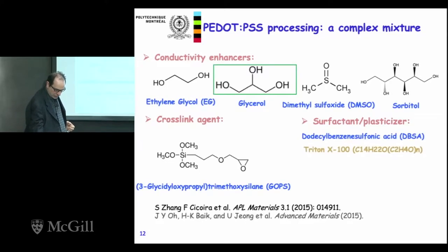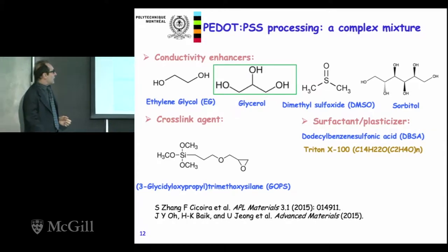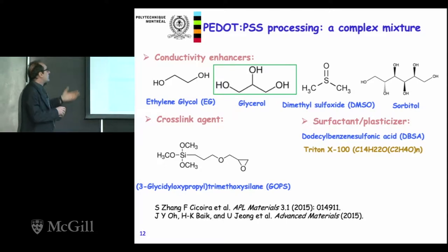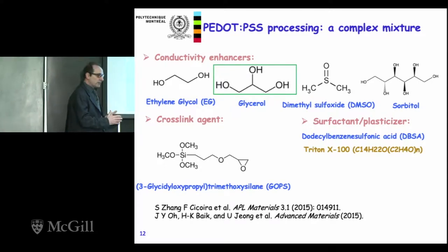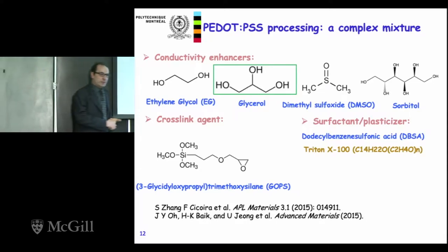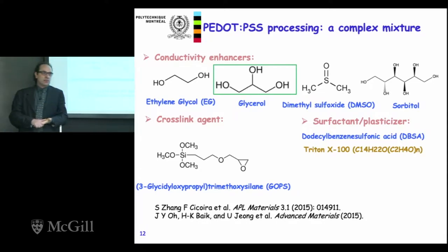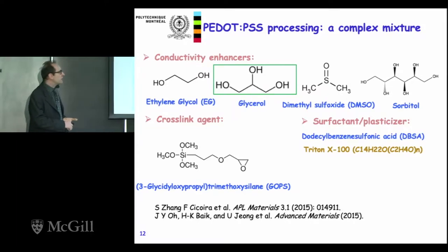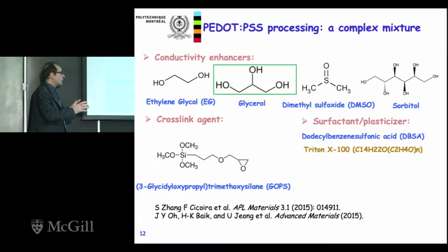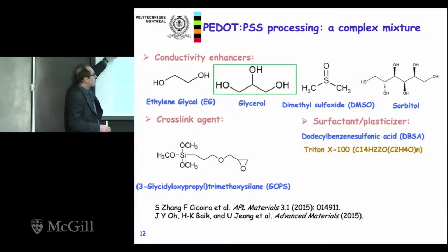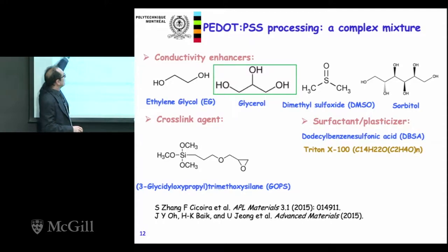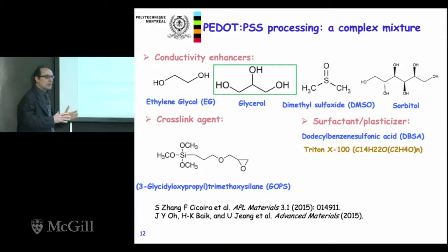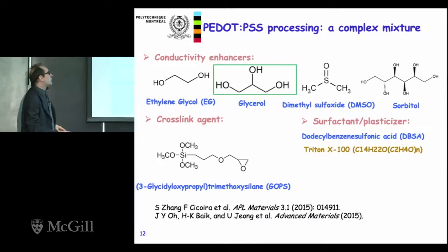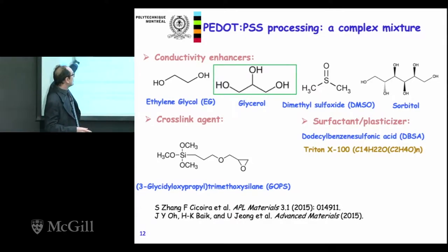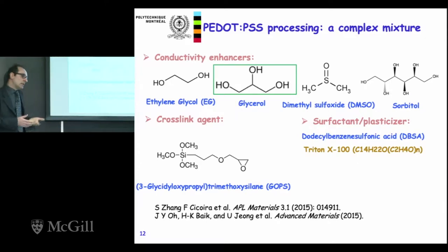Actually, we deal with a mixture, which is something I realized that chemical engineers like a lot to deal with, mixtures. So essentially, what we do, we can buy this material from a company, and it's sold as a water dispersion. But if you use this material as it is, you get very low conductivity. So what you want to do first is to improve the conductivity. And actually, for some reason that I will not talk about today, the conductivity of this material increases by orders of magnitude if you mix it with one of these compounds, which in most cases have OH groups. So the increase of conductivity has something to do with these OH groups, but it can be up to 3 or 4 orders of magnitude. So the first thing you have to do is to mix this commercial suspension with this material and process a film out of it, and then you can increase the conductivity.